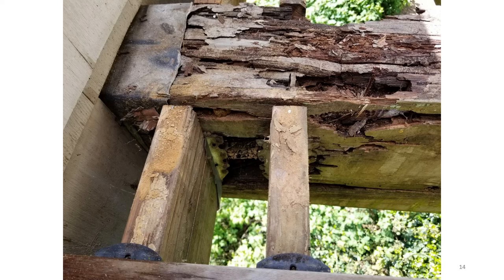And so again, if a piece of lumber is going to be exposed to water, you need to make sure that it will dry out fairly quickly. If water remains trapped long-term, rot and fungal decay can set in. Now, the cutoff point depends, of course, on species, condition, temperature, etc. But generally, if moisture content is above 20 to 30%, wood decay becomes a risk. Controlling moisture content and protecting wood is a primary concern in wood construction, and great care needs to be taken to protect wood from water from both the weather and from moisture in the soil. And we will certainly discuss this more as we move through the course.